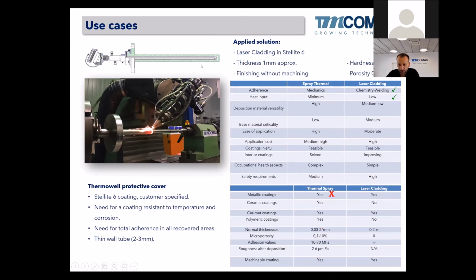As you can see here, the part has a thin wall. It's a thin wall tube. It's not a tube, it's a blind tube. It's a thin wall, okay, 2-3 millimeters. So just imagine now that you have to clad Stellite 6 by TIG or by rod welding in a 2-3 millimeters thickness tube. You will have to stop, and you have a lot of risk of penetrating, of making a hole in the tube.